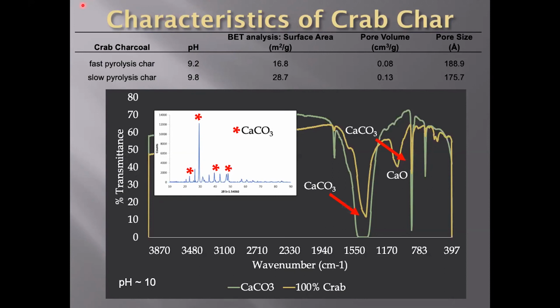I'm just going to show you a little bit of our evidence that tells us what the crab biochar is composed of today. Notably, the biochar itself is also very basic. It has a pH of around 10. And that makes sense when we look at the composition of the biochar. So the bottom spectrum is an FTIR spectrum, and the peaks that are shown in light green, on my screen anyways, are pure calcium carbonate. And when you compare that to the peaks that are shown in the sort of yellowish color, that is the 100% crab biochar, and you can see that it is largely matching with the calcium carbonate.